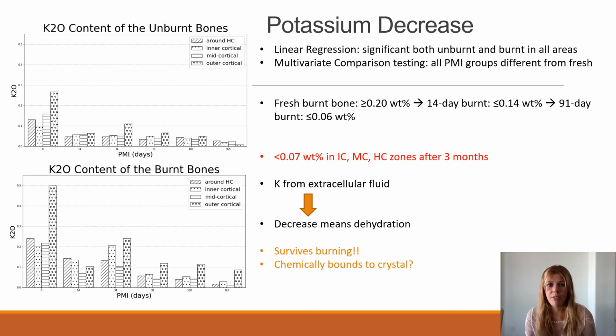Potassium was previously found to be localized in the removed organic bone material in another study and was suggested to be present mainly in a labile state. But the fact that organic material was removed by burning in the present study, but potassium was detectable by the microprobe in the thermally transformed bioapatite, makes it possible that potassium may be chemically bound to the crystal.